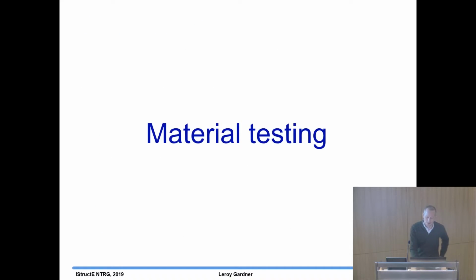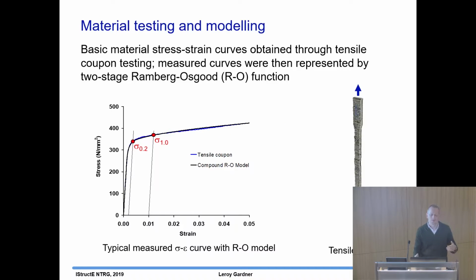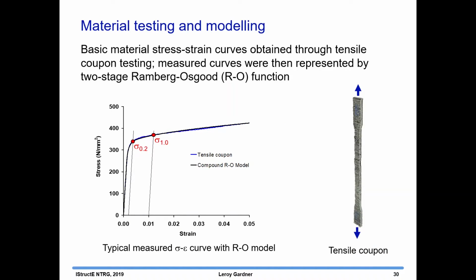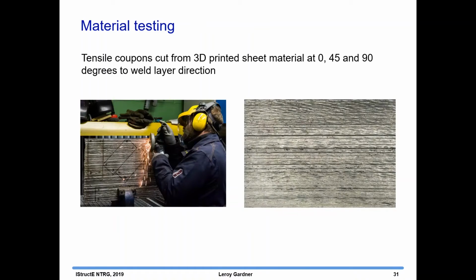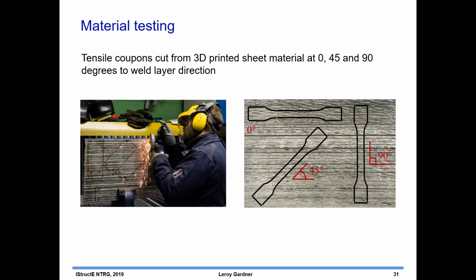Okay, so material testing first. We wanted to know what are the basic material stress strain characteristics. So we carried out a series of tensile coupon tests. And we cut coupons from material printed in the same way as the bridge. And we cut the coupons at different angles to the weld layer direction. So we cut coupons out at 0, 45 and 90 degrees to the layering direction.